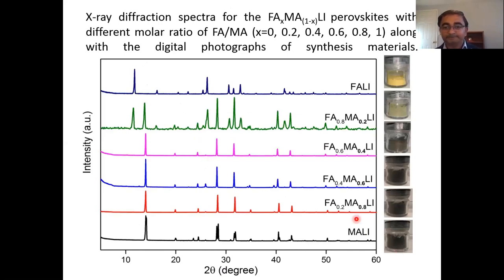I started with MALI, and I used the ball milling technique, a very simple technique to synthesize nanomaterials. Ball milling is very cheap and very simple in the ambient atmosphere. And I am successful in making this perovskite in a powder form. And then I put some formamidinium in that, and using this formula, FAMALI, I synthesized the range of material from MALI to FALI.